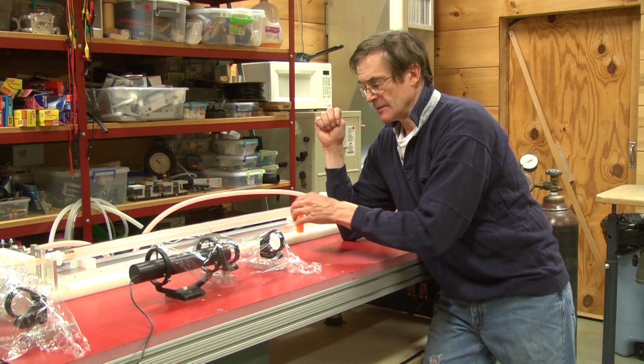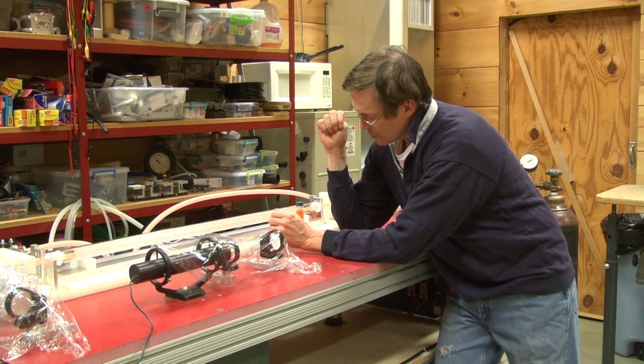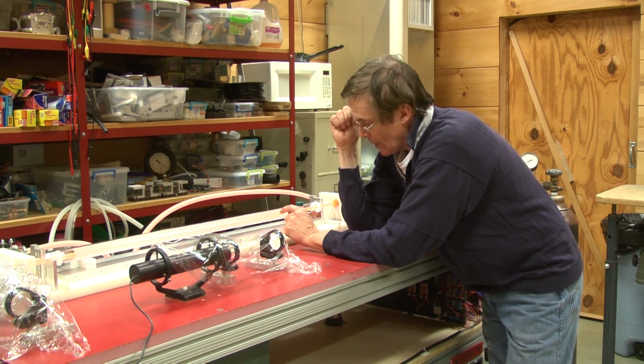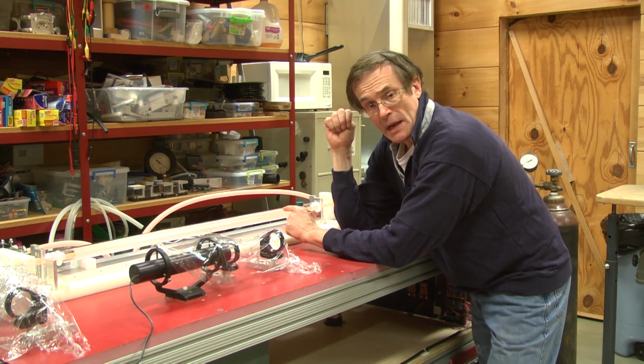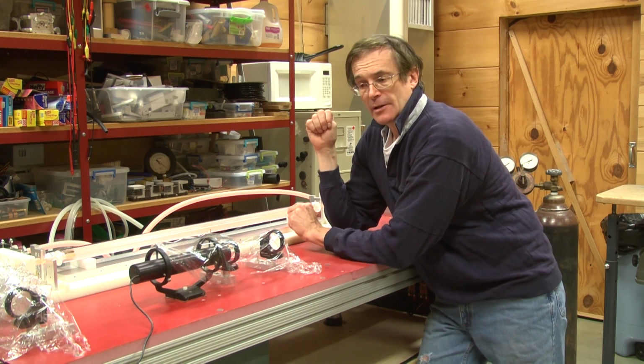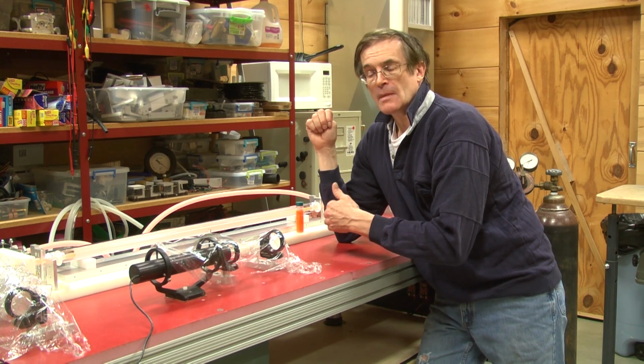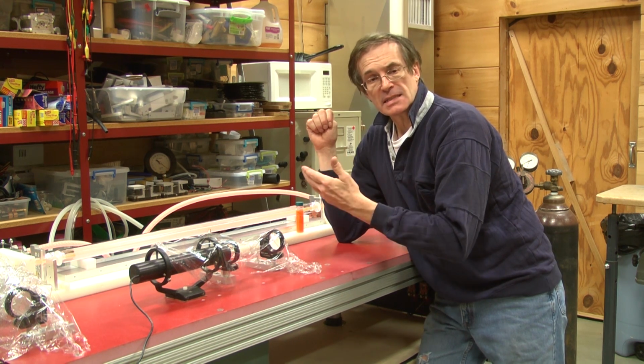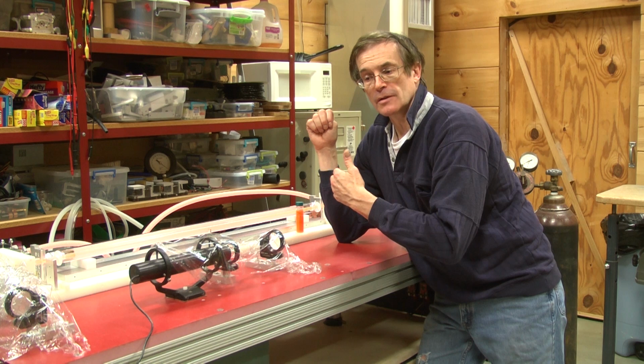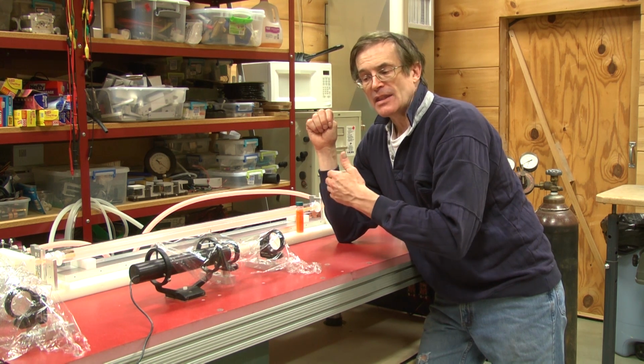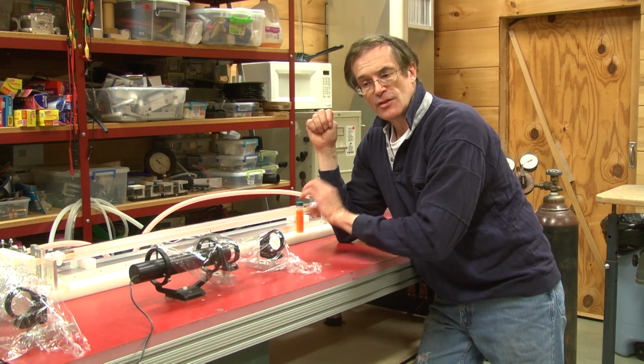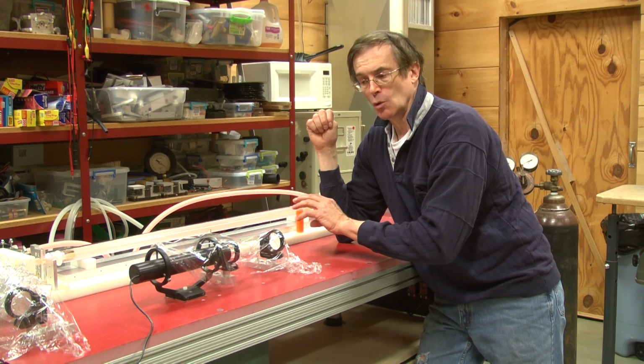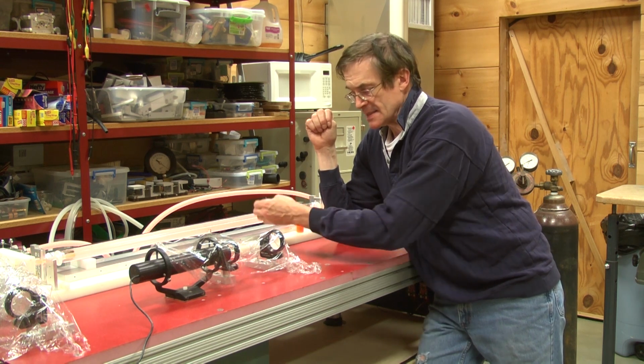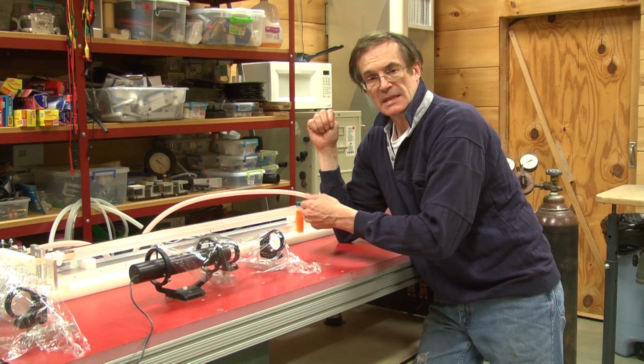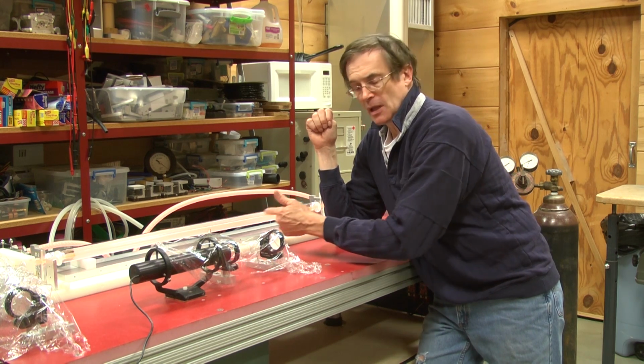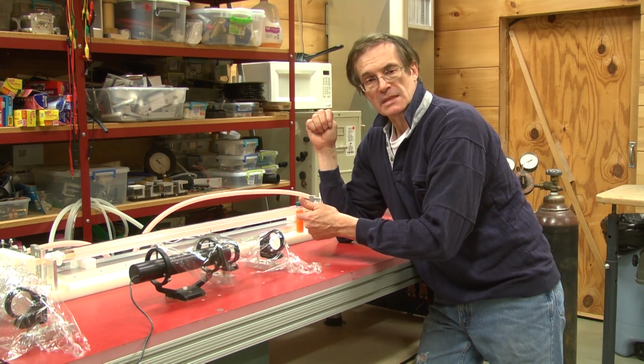What that does is, instead of having a mirror surface on the inside, you have a different surface. I don't know if you're able to see inside here, but as I took away one half of this reflector, the inside looks white. That's because the reflective material that I have on there is a diffuse coating of barium sulfate. Any of the diffuse coatings, whether it's magnesium oxide, alumina on ceramic tubes, or even polytetrafluoroethylene, which is Teflon, have enormously higher reflectivities than mirror-like materials like aluminum and copper and gold. So even though the reflection inside is not limited to just two bounces, and it may take five or six bounces for the light to get from the lamp to the medium, it's still a more efficient means of coupling.